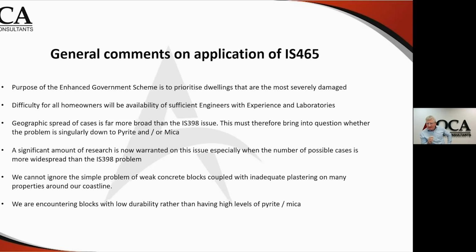But what I'm finding is I've got 2 layers of plaster. The outer layer is the thinnest of all, but it's also the strongest layer, which is completely the wrong way around. The strongest layer should always be on the inside. And as you get out towards the outside of the building, the render should get weaker, so it can deal with the thermal cycles of summertime and wintertime more effectively. That is rarely found. I'm saying here at the end that we are encountering blocks with low durability rather than having high levels of pyrite and mica.